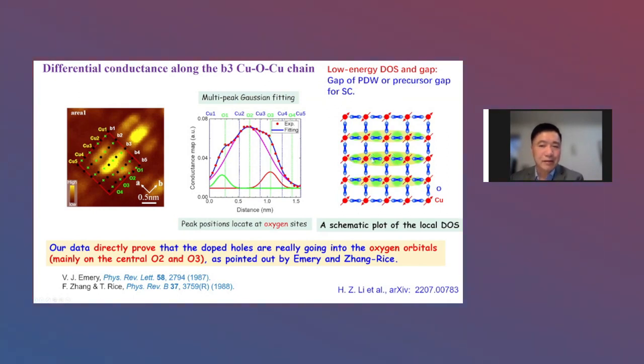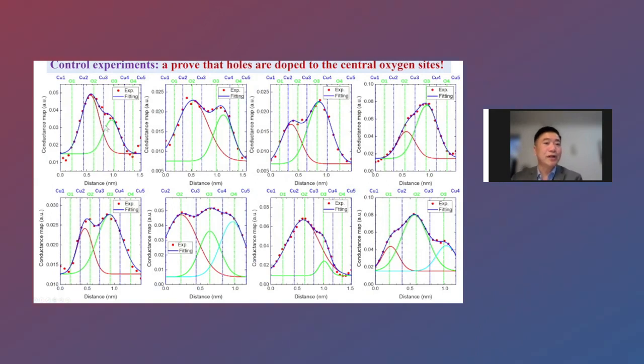This density state is high and forming a small gap, which is nearby the Fermi energy, which we think is very important for the pairing. This slide shows the control experiment to prove that the holes are doped to the central oxygen site. You can see these peaks appear on the oxygen 2 and oxygen 3, okay? So this is a control experiment. We have measured for such.